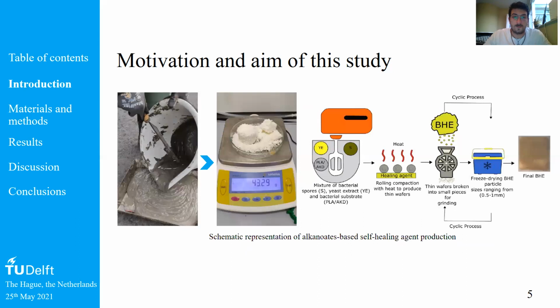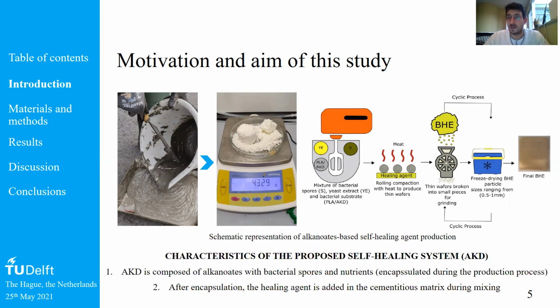We know that what we do with our healing agent that is indeed alkanoid based is basically that we get biomasses from water plants, such as those that you see on the left side of the screen, and then out of these, through certain bioreactors at the Faculty of Applied Sciences, we get this bioplastic that looks like the powder that you see in the second picture from the left, and then we merge this bioplastic with nutrients for the bacteria and bacteria spores, and through a certain production process of the healing agents, then we get to the final healing agent that is powder-like, generally between 0.5 and 1 millimeter in dimension. And then we embed this healing agent into the matrix while we mix our specimens.